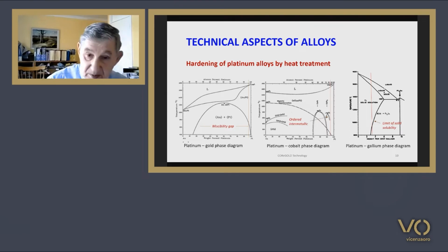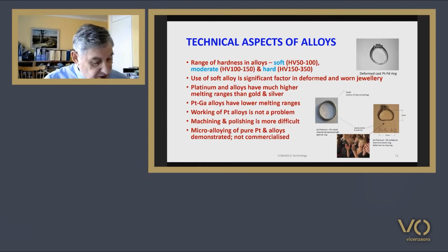From the table of alloys, it is clear that some alloys are quite soft, with a hardness value lying in the range of 50 to 100 Vickers. Some have a moderate hardness value, 100 to 150 Vickers, and others are quite hard, with hardness in the range 150 to 350 Vickers. The higher values are usually when in the age-hardened condition.